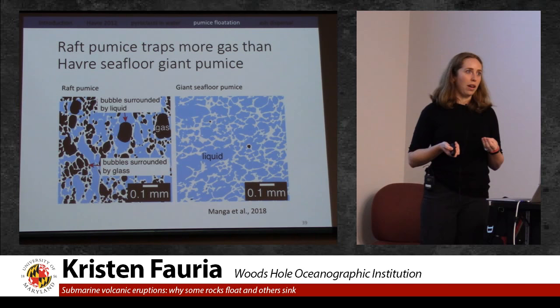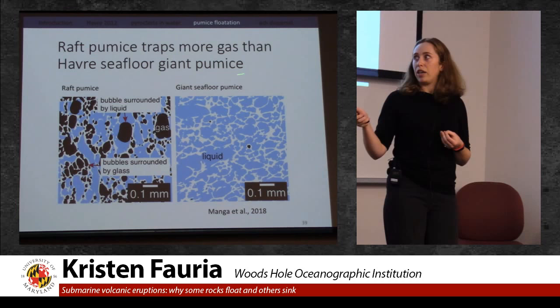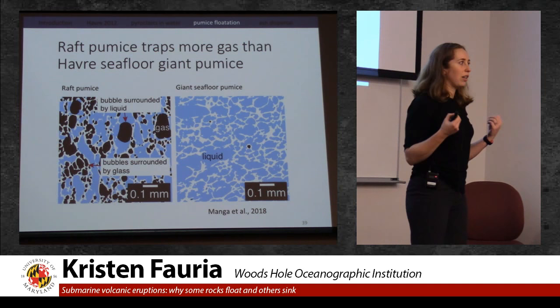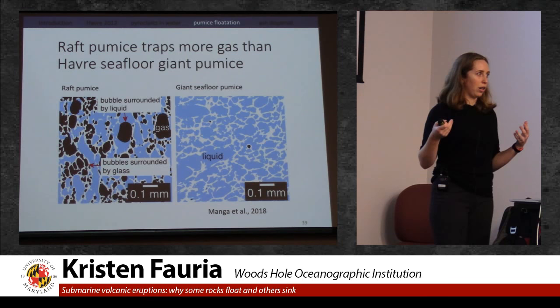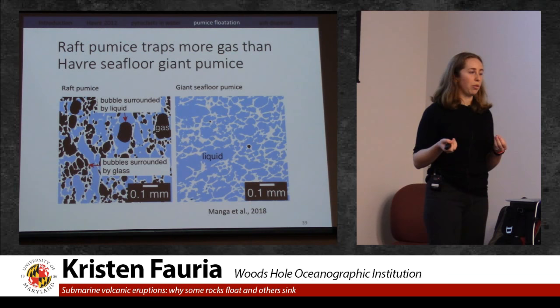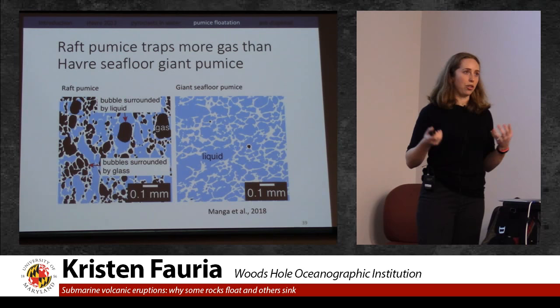And a colleague of mine, Megan Jones, measured the connected porosity of these two samples, and she found that the raft pumice does have some isolated disconnected porosity. And that is important because it means that no matter how much time you leave the pumice in water, it's not going to be able to absorb that water. But that isolated porosity isn't quite enough to allow the pumice to float on its own. It still needs some residual gas trapping via surface tension.